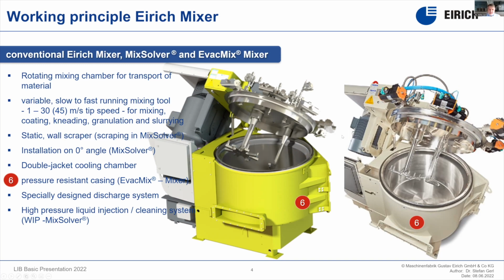We developed the vacuum system in the 90s of the last century. This means we are putting the rotating mixing chamber into a pressure vessel so that we can apply vacuum parallel to the processing. This means we can produce a bubble-free coating slurry during operation while applying vacuum. We typically have a discharge system concentrically in the center of the mixing chamber to save height and also to be more flexible with the cooling systems on the complete bottom of the machine. We have designed special discharge systems either for the liquid slurry or also for the structured dry mix you will see later on.